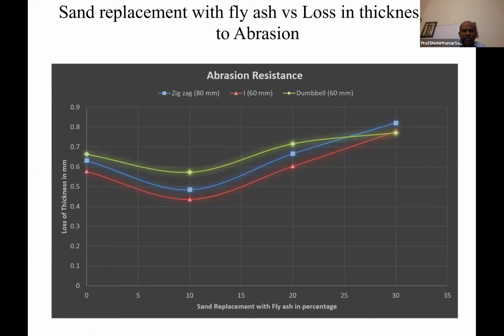Abrasion resistance. Actually, abrasion testing I will show you. I have shown you the equipment. Even the video is there, on how to cast it and how to test it. The abrasion value is nearly 0.7, and abrasion decreases with 10%, then increases with increase of fly ash for different shapes.